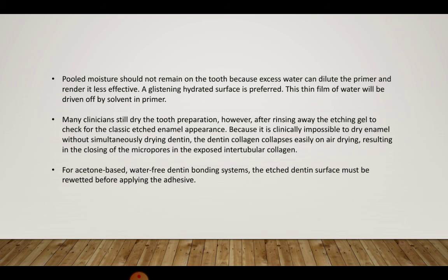For acetone based water free dentine bonding systems, the etched dentine surface must be re-wetted before applying the adhesive. So, there are two kinds of primers: those which are acetone based but water free, and those which are water containing primers.